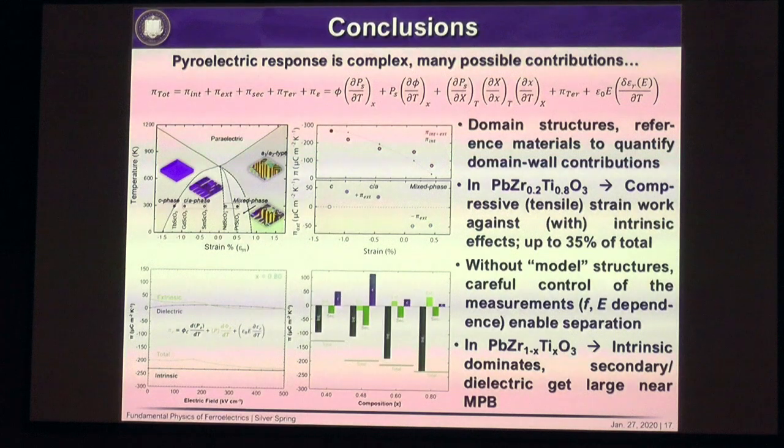So at 0 bias, there's none, and it peaks for each sample at a slightly different temperature, near where it switches, of course, in these systems. But depending on what kind of applied bias you have, you could have a really deleterious effect happening in your system if you're applying a bias during the measurement. You just need to know that these are there. You avoid them all at 0 bias, but it is a function of field.